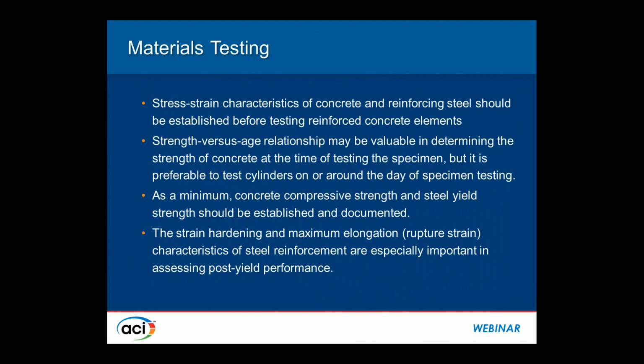but these days may not coincide with the actual test date, and hence it is a good practice to establish strength versus age relationship by testing cylinders at different ages so that one can predict actual material capacity on the day of structural testing. But as a minimum, one has to report compressive strength of concrete and yield strength of steel. Obviously, this is the bare minimum information needed to interpret test data and assess the results.